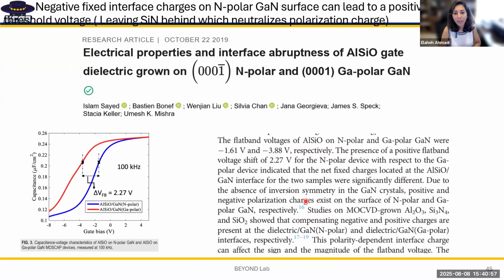So now again, we still need to investigate this further. But what we think is happening is that basically the negative fixed interface charges on nitrogen polar GaN can lead to a positive shift in the threshold voltage, and that could be the reason. Silicon nitride, actually, the work by Tanmay and others in Umesh's group has shown, neutralizes polarization charge. So that may be the reason we can actually get E-mode performance by using aluminum silicon oxide. But again, this is the work that we are now focusing on to better understand what's happening at the interface.